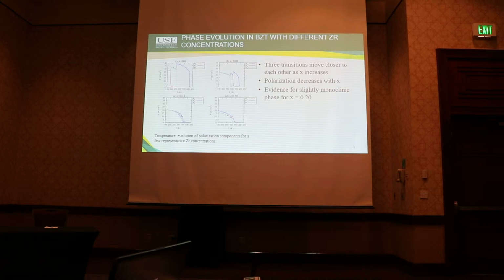At 14%, we see that there's a pinched phase transition where it goes straight from the paraelectric cubic to the ferroelectric tetragonal. And then at 20%, we find evidence for a slightly monoclinic phase. And this will be investigated later on in the presentation.